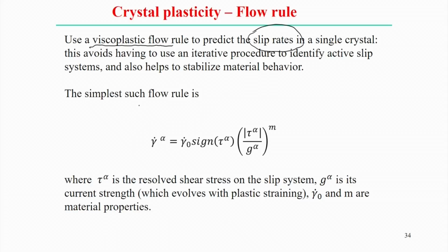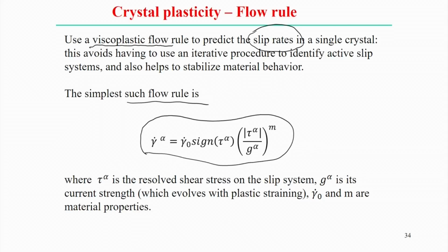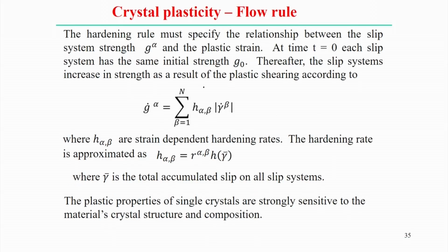So, this is one of the simplest flow rules generally used, and we see it in terms of the rate. This rate is significant because we have considered the flow of the material as viscoplastic flow. So, for this viscoplastic flow of the material, we can use this relation, where tau is the resolved shear stress on the slip system, g is the current strength which evolves with the plastic straining, and gamma 0 dot and m are material properties. m is not the Schmid factor here; it is one of the material constants and depends on the properties of the material. So, these are the typical flow rules we can use in the crystal plasticity model.